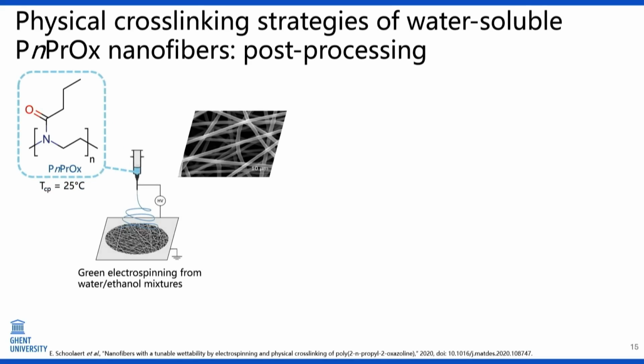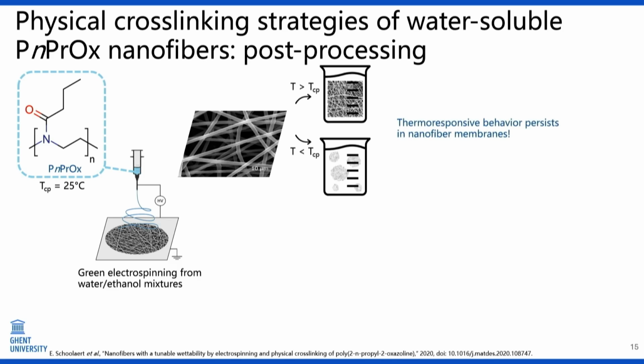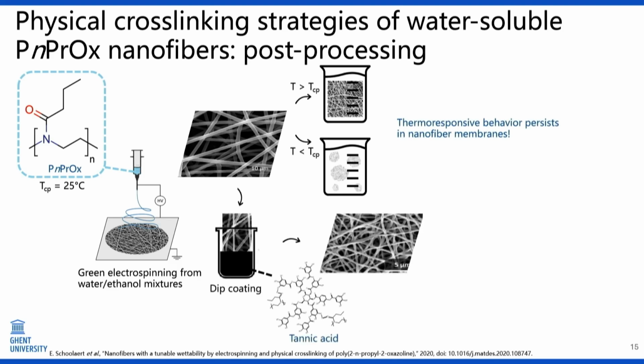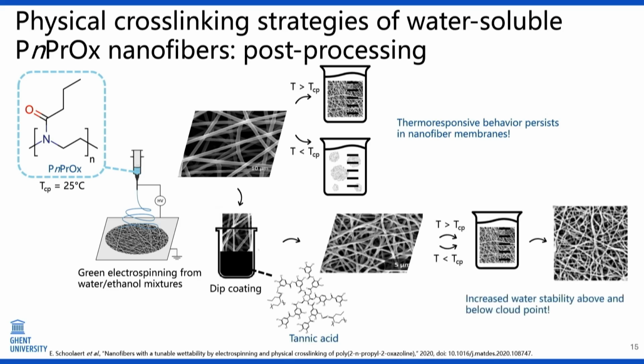We do not always need chemical cross-linking. For some applications, a physical cross-linking is good enough, and this is illustrated here for the PnPrOx polymer. Most of these polyoxazolines are also thermoresponsive polymers, and so they have a cloud point, meaning they're water stable above the cloud point, but water soluble below. We take advantage of this water solubility to spin them from aqueous solutions, but then we can dip coat them, in this case with tannic acid, at temperatures above the cloud point and make them water stable over the full temperature range, both below and above the cloud point.